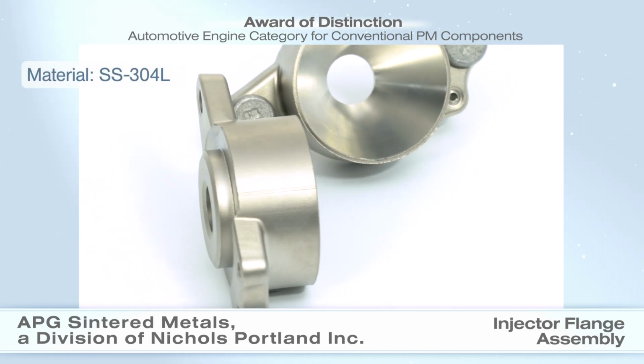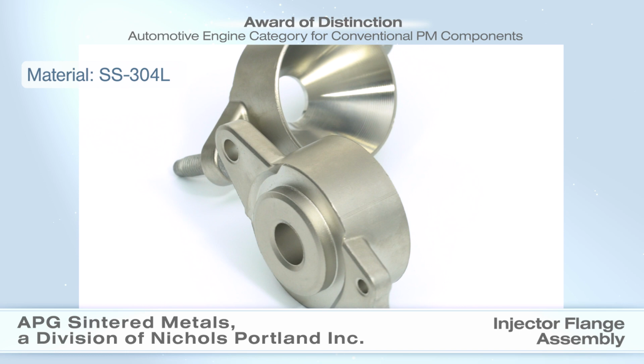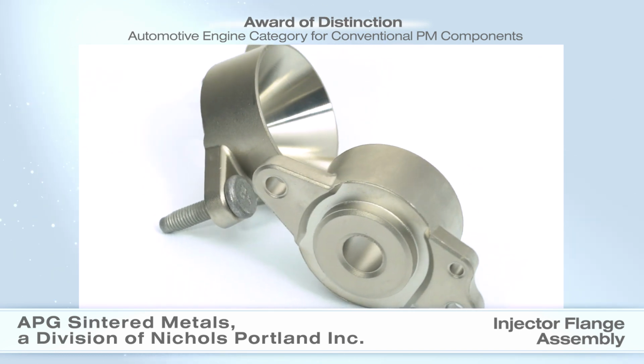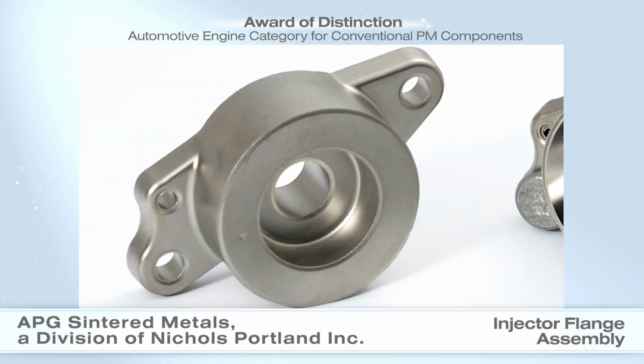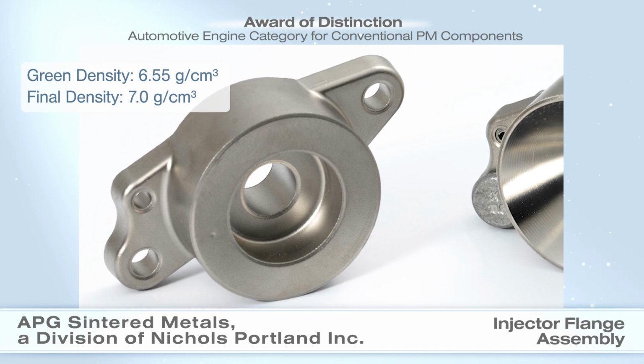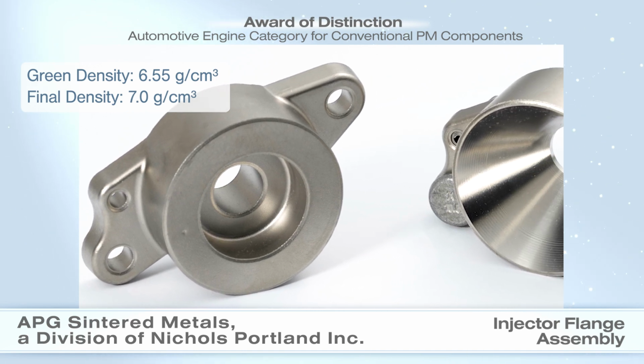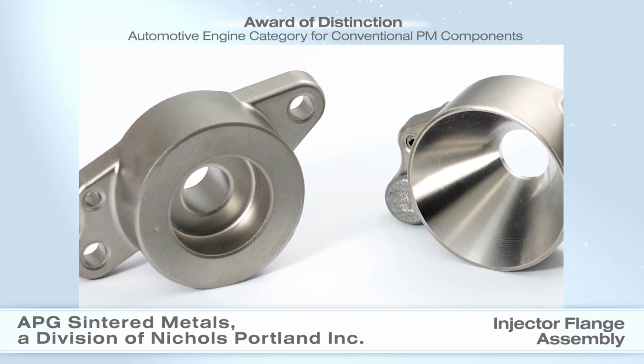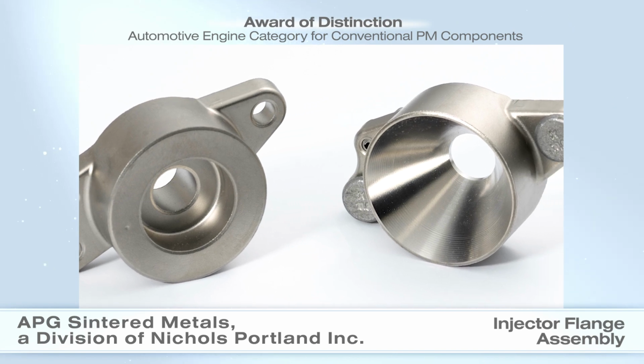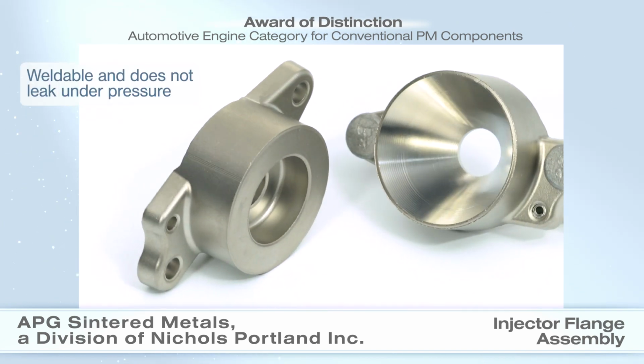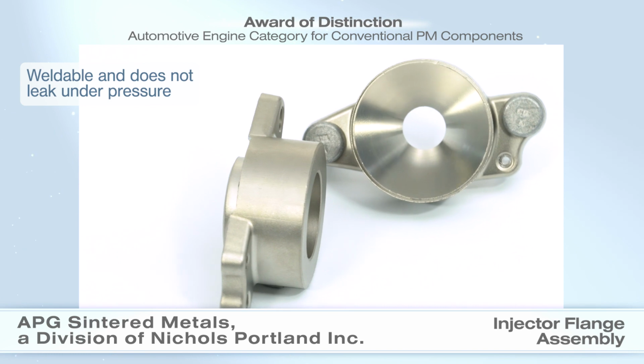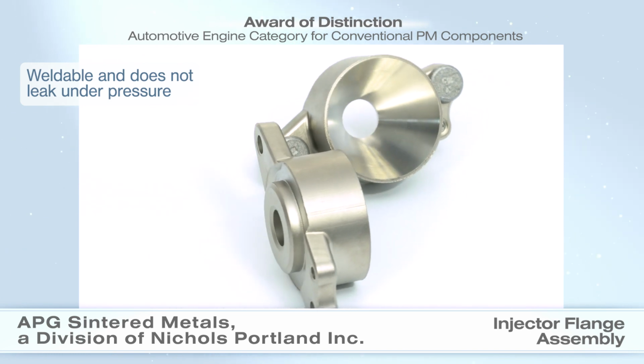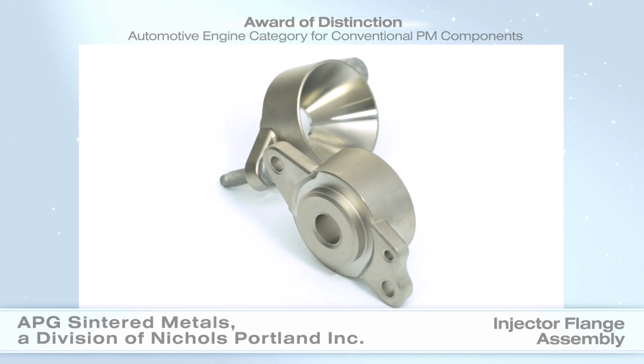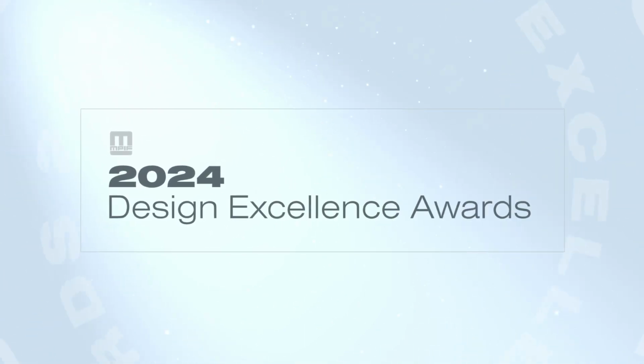Austenitic 304 stainless steel was selected for its combined good corrosion resistance and weldability. Due to the low compressibility of the powder, the parts are sintered at 1350 degrees Celsius in hydrogen to reach the final 7.0 grams per cubic centimeter density. Minor machining is required on the inner diameter and conical counterbore. After welding, the assembly does not leak when under pressure.